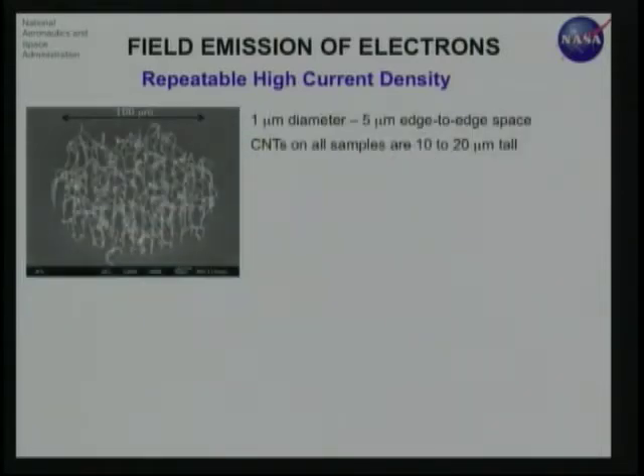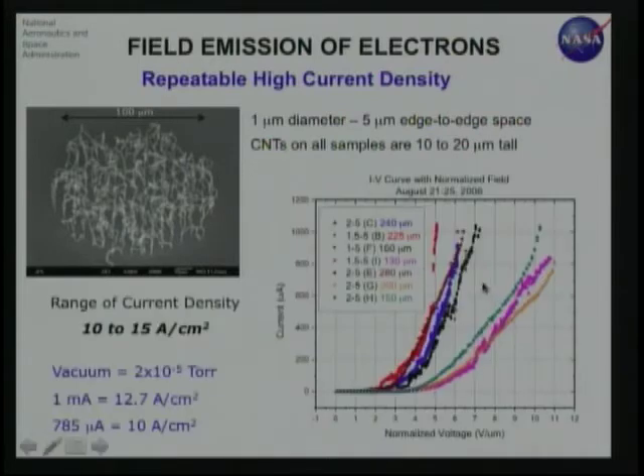So we ended up making large area samples, which are 100 microns in diameter. Here's the footprint. It's about 100 microns, and they're all 1 to 2 microns diameter bundles, spaghetti kind, spaced 5 micron apart. And they consistently produced very high current densities. So these are all at the 10 to 15 amps per square centimeter, each one of them.